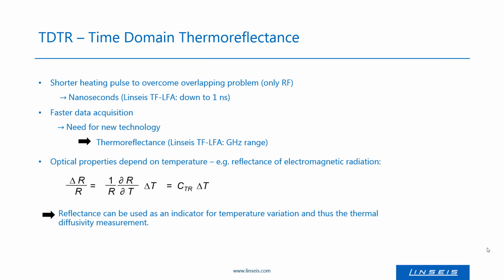We use the fact that the reflectivity of a material is temperature dependent for the measurement of the local temperature rise. For this, a secondary detection laser continuously measures the reflectivity of the heated spot in order to record its normalized temperature. This is used for the determination of the thermal diffusivity. To be able to perform the measurements with this method, a reflective layer with a known reflectivity behavior independent of the temperature is needed.